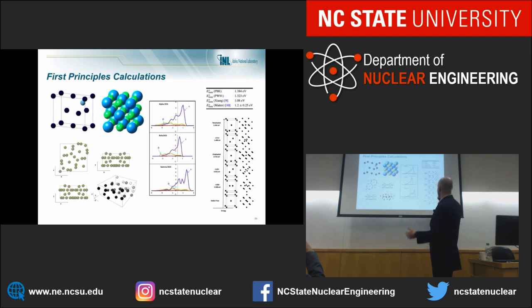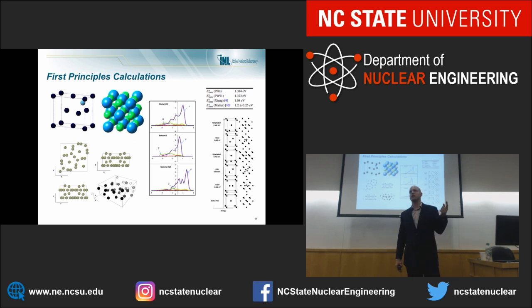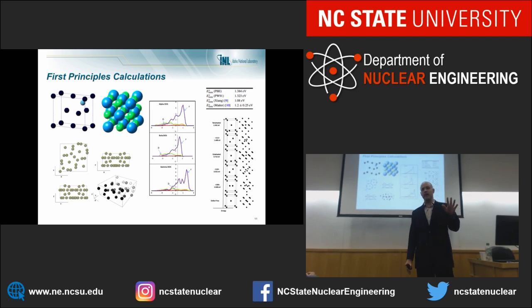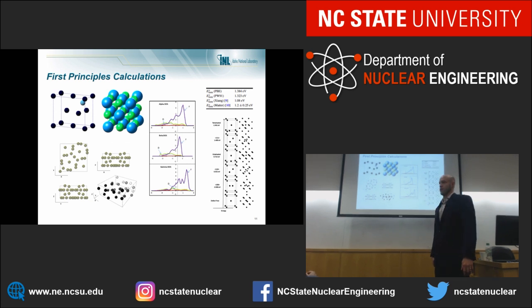And so we were able to look at a number of defects in these systems, and they actually compare OK to the one vacancy formation energy experimental work that was done. And then since this table was made, there's been a secondary positron annihilation experiment calculating vacancy formation energy in BCC U, and that result further matches our results from this work.